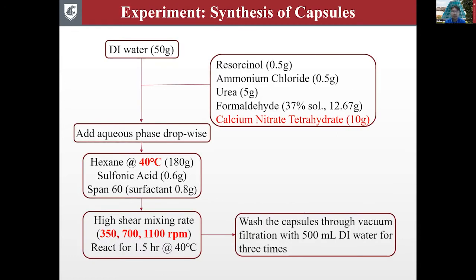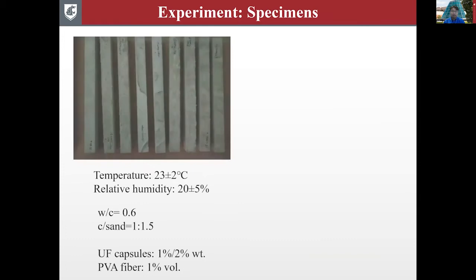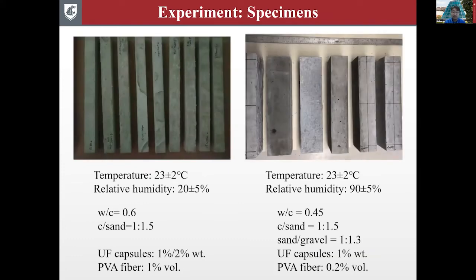So here's the synthesis procedure of microcapsules. It's a water-in-oil polymerization process. We add the aqueous phase containing all the chemicals into the oil phase drop by drop, and we selected 3 agitation rates for tuning the size of the microcapsules. And we prepared 2 types of specimens, which are cementitious composite specimens used for the shrinkage test, and concrete specimens for freeze-thaw durability tests. The curing condition and mixture design are listed below. The content of urea-formaldehyde microcapsules is 1% or 2% by weight of cement, and the content of PVA microfiber is 1% or 0.2% by volume of specimen.